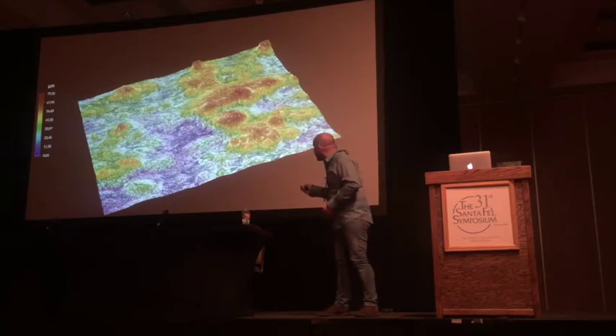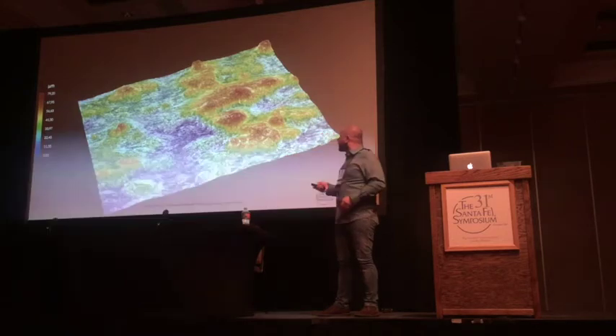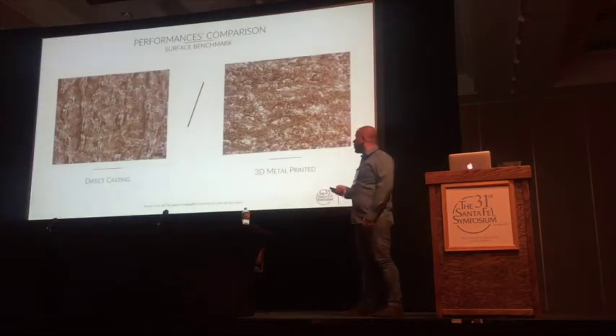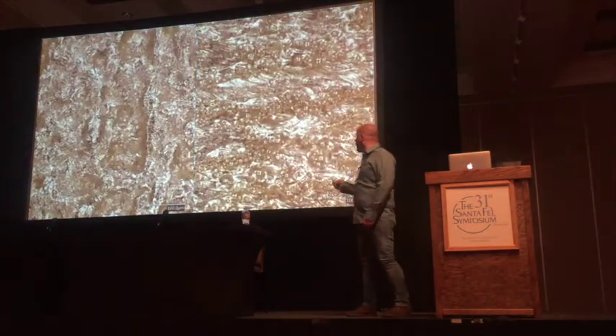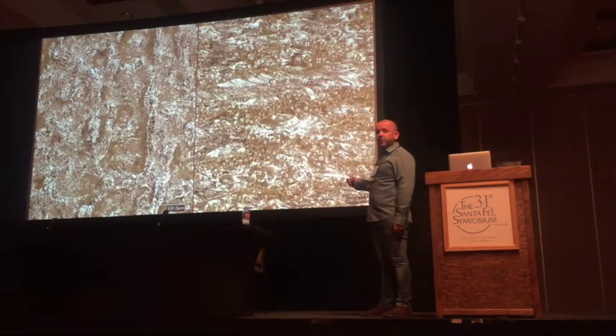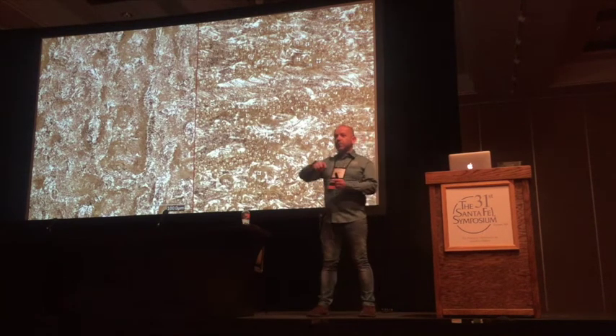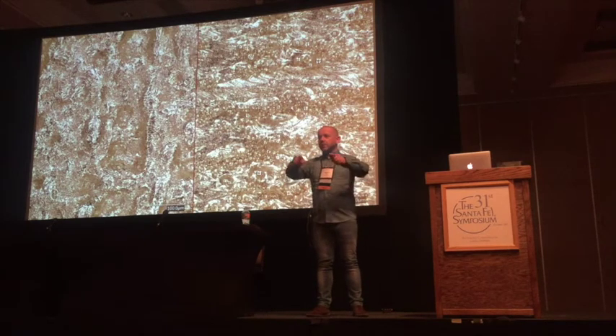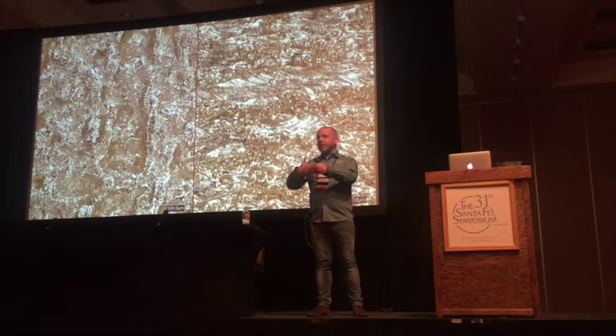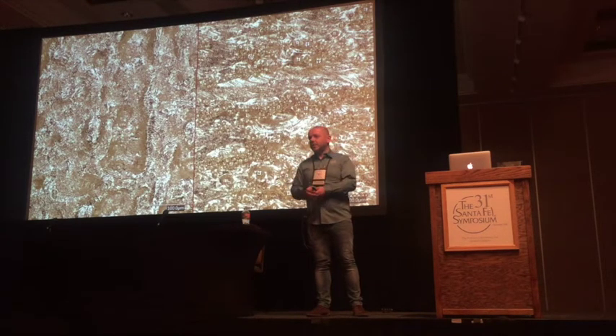The image is quite accurate, because I don't know if you are able to see, but here we have all the particles, small spheres of powder, everywhere. In fact, the biggest reason for roughness in 3D metal printing, as you can see in the image at 500 magnification, is all those particles that are sticking. When we scan the outer line, we melt, and of course the particles touching the melt stick to the part.